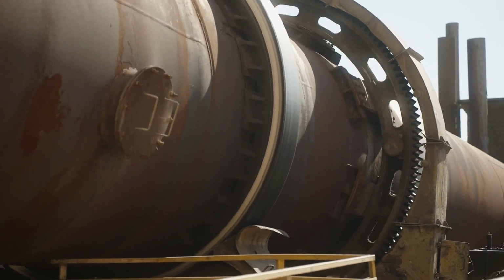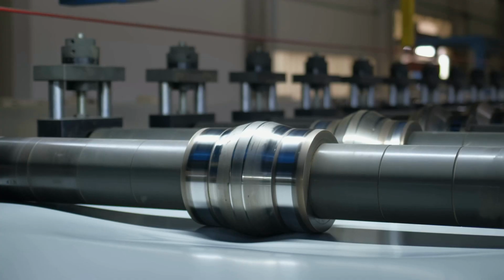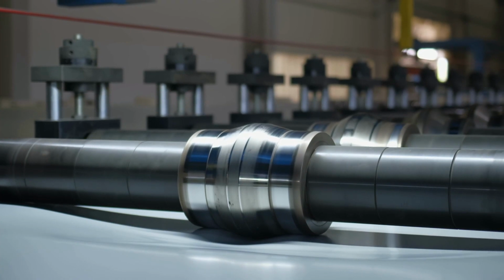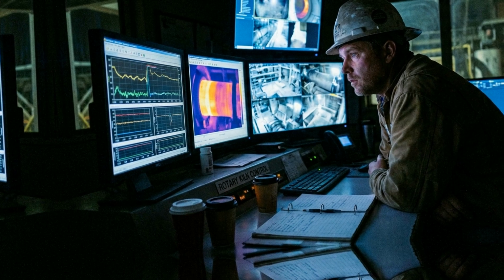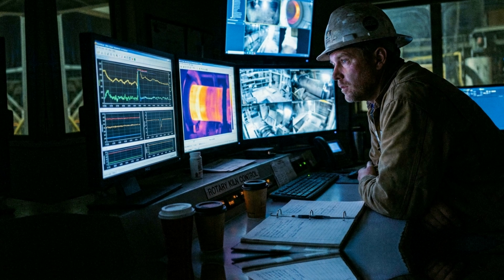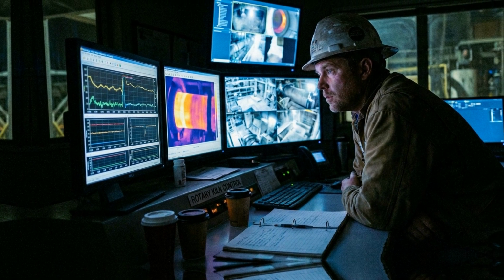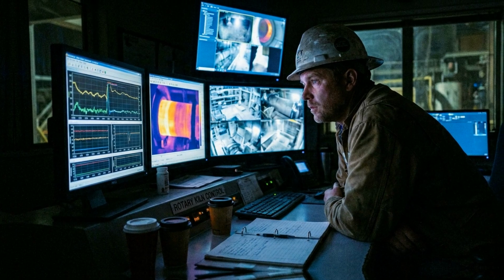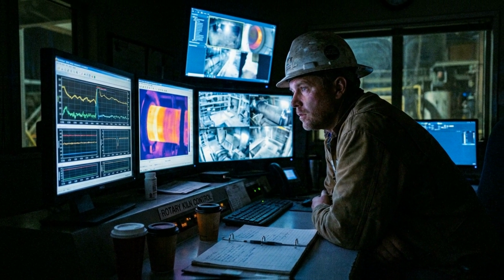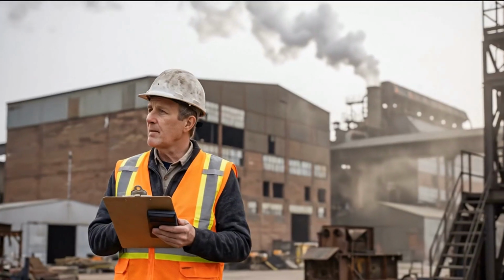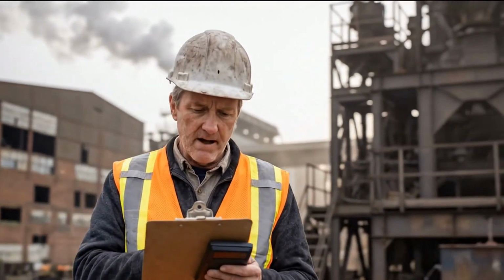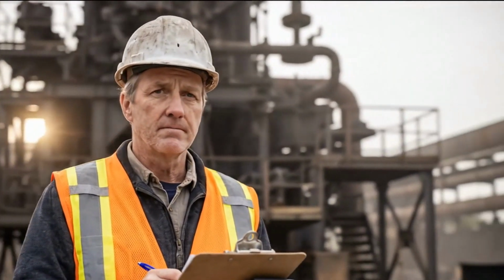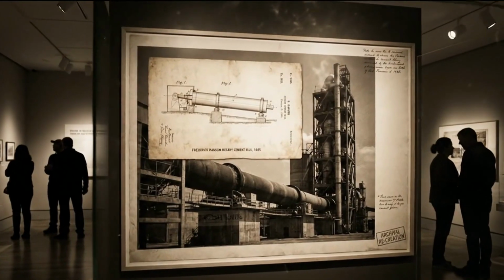Kiln operators monitor axial drift continuously. If the tube walks too far toward either end of its support rollers, the consequences are severe. A kiln that derails its own support system is a significant industrial incident, so they watch it constantly. The kiln runs for months between planned maintenance stops, turning at 1 to 4 revolutions per minute, day and night, through seasons, through shift changes, through everything. Stopping it means a multi-day cooling and reheating cycle that costs significant production. The economics of cement manufacture strongly prefer a kiln that simply never stops.